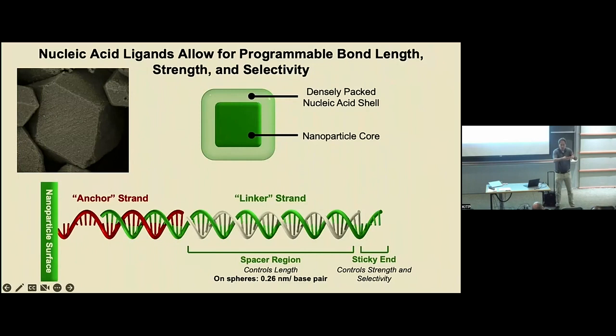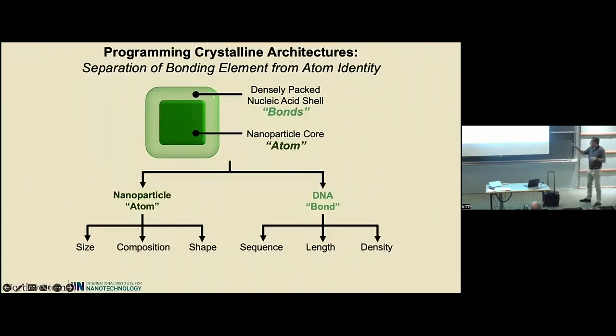If they're too long, you get stuck in kinetic traps. If they're short, 4 to 6 bases, they're strong enough to hold the structure together, but weak enough to allow the system to equilibrate and find the thermodynamic minimum. Now, this kind of gives you a clue in terms of how you can begin to think about deliberately programming the formation of different types of architectures. Because there are some similarities between atoms here, but there are big differences.